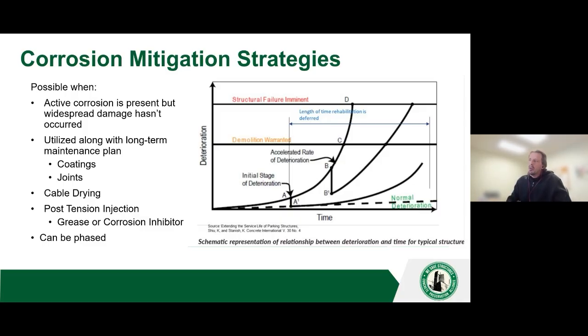So if we're going to do a corrosion mitigation strategy, we really want to look at coatings, joints, areas where water has been getting into the strands, right? We have to address that. So we can do the corrosion mitigation, but then right on the tail end of that, we have to make sure that water doesn't get back in. Cable drying, it's exactly that, right? So we have methods to run dry air through the cables, not unlike the moisture testing, to dry out the cables. And then once that is done, we can either re-grease them, inject grease, or a corrosion inhibitor.